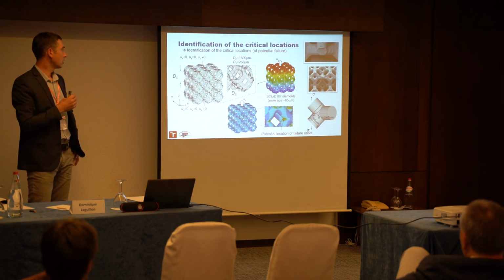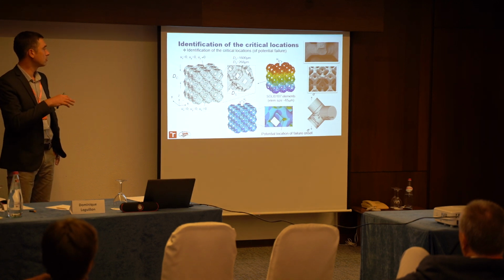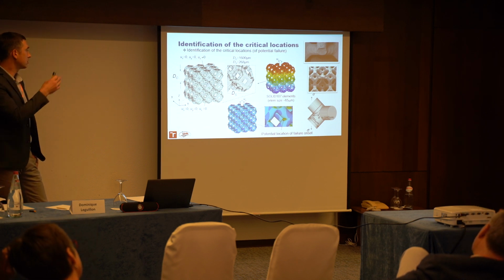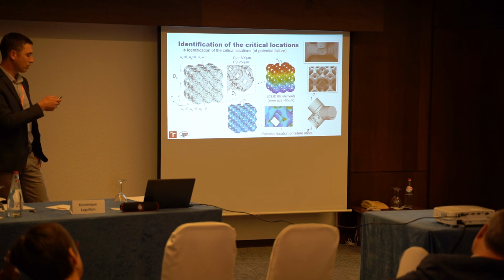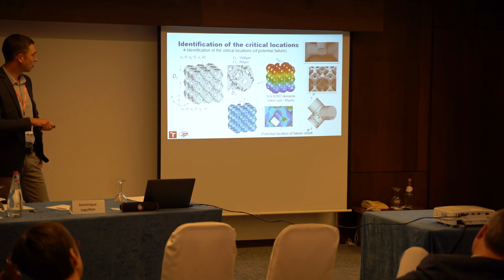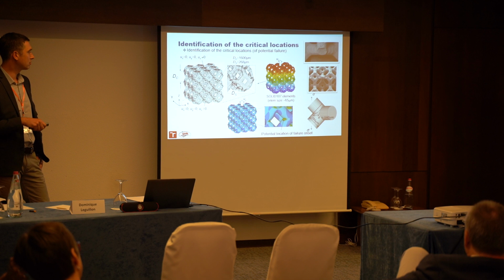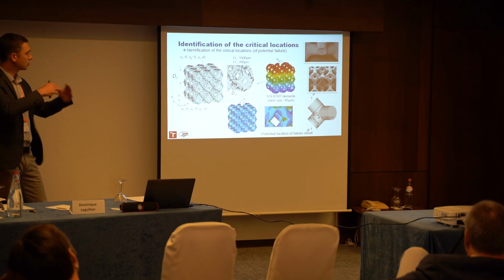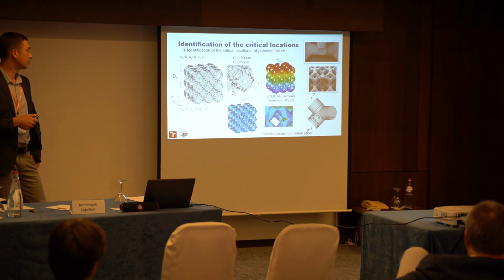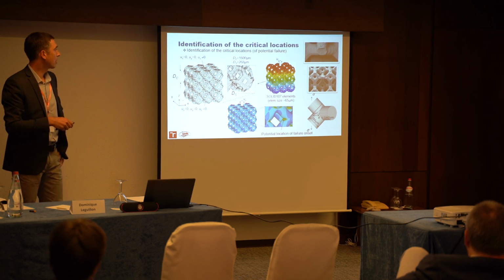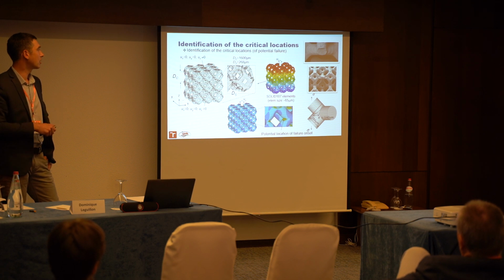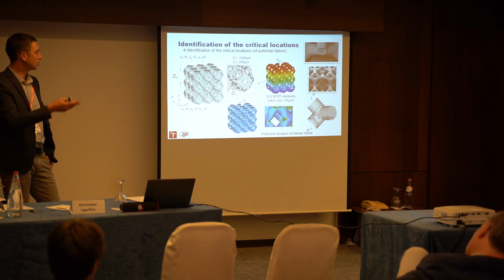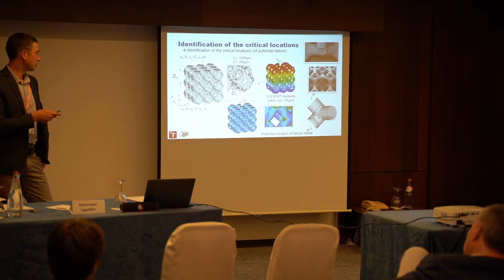So before we could apply the coupled criterion, we had to know where the critical location is where the potential failure can occur. So we did a preliminary simulation where we loaded the structure by displacement, and we took a look at locations where concentrations of stresses are present. So here, these corners or connections of struts, we can expect that it will be the first place where the crack will initiate. This was also confirmed by the microscopic analysis of the broken foam structure from the experiment. So the failure comes from this corner, it goes a little bit inside, and then kinks so that the strut breaks. So this was the first necessary calculation.